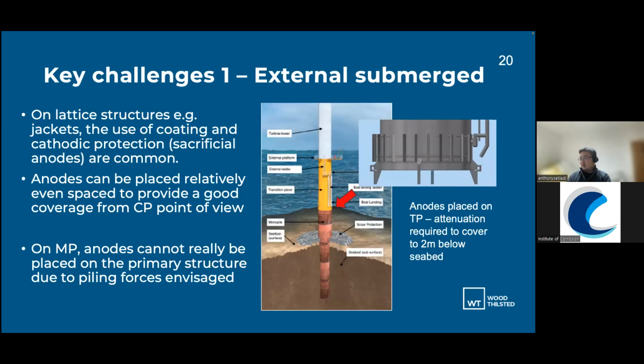So the key challenge one is on the external submerged zone. On lattice structures, such as jackets and subsea templates, if we use traditional cathodic protection using galvanic anodes, aluminium anodes, the spacing of the anodes is relatively easy because you can pretty much put them equally along the structure.